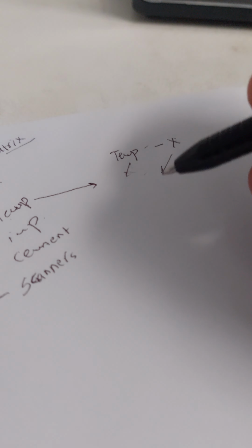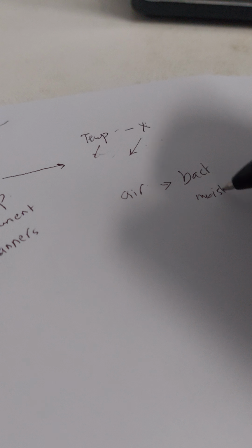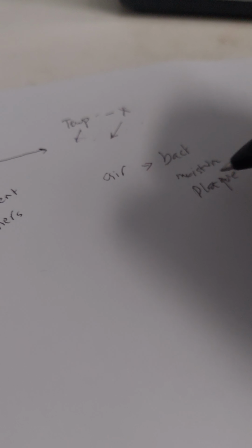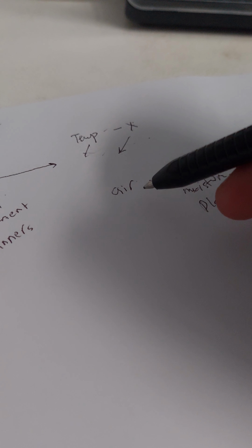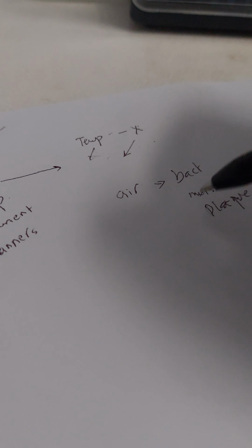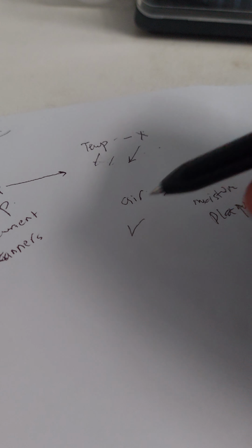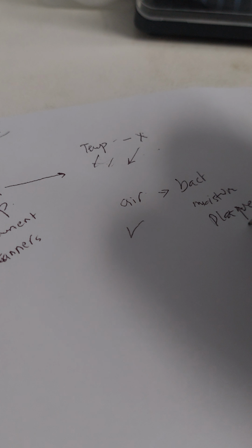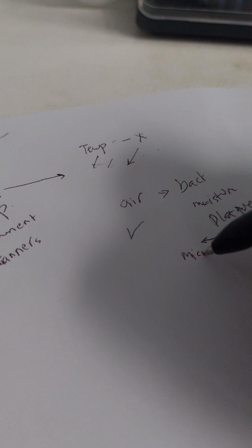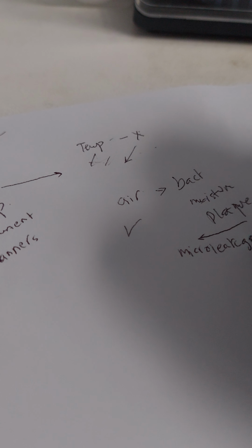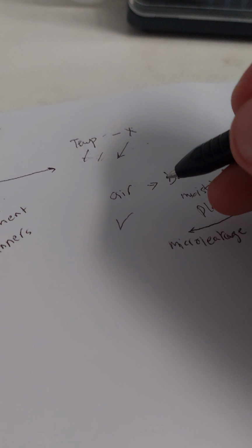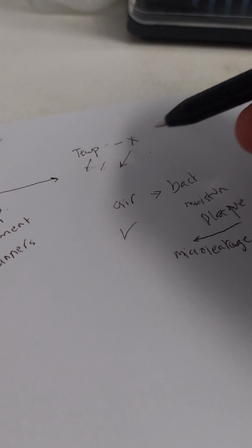There is another problem with long-term temporization. Now, the air inhibited layer will not stay as it is. It traps bacteria and attracts moisture. It also attracts plaque and all of the polysaccharides attached to it. So all of these are attracted in this air-inhibited layer beneath the temporary. This will cause the breakdown either of the temporary material or the core material itself, and even might cause a failure of the core material by microleakage, because it's failing at the point of the presence of the air-inhibited layer. So this might cause failure of the core, not only the temporization.